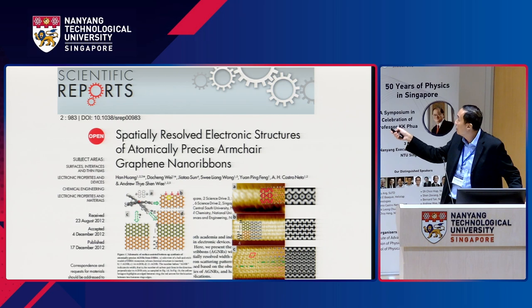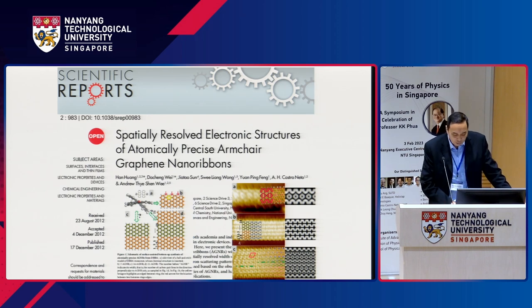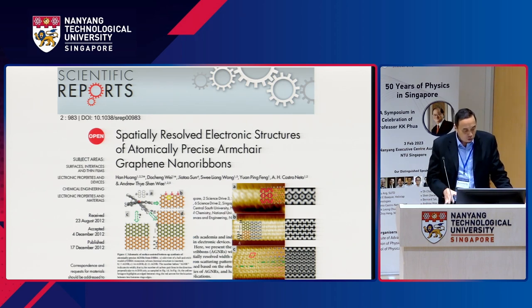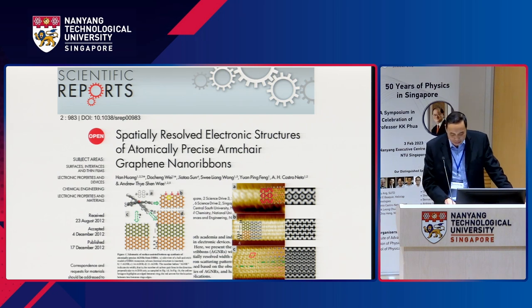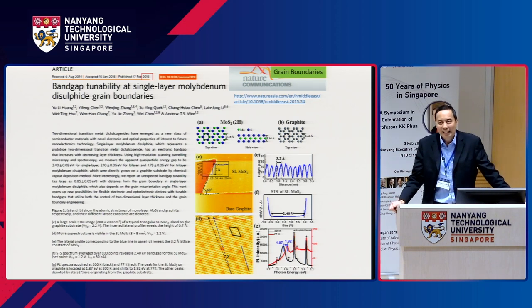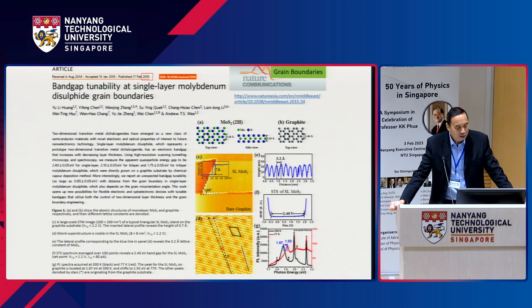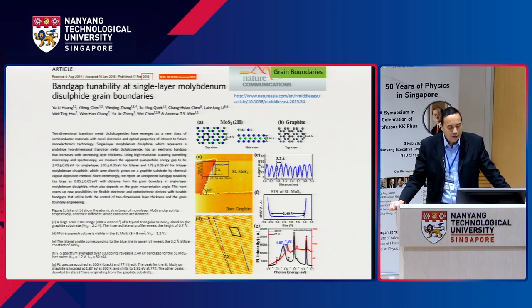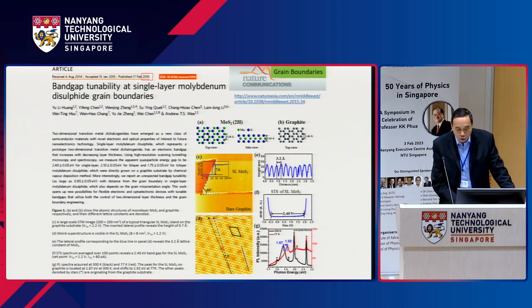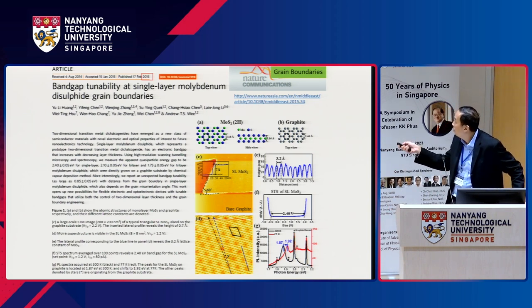So you can see all these patterns. These are really the electronic structure, these are the simulations, and these are the STM images. So we had fun with this for a while. This is 2012. And then, like everybody else, we moved on to different 2D materials. These are the transition metal dichalcogenides. The first one that people normally study is molybdenum disulfide. We had some difficulty getting good STM images and clean surfaces, but finally in 2014 or so, we managed to get fairly good images of this molybdenum disulfide.